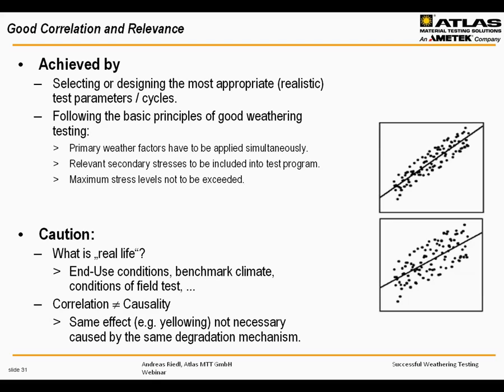So if you would like to test at, let's say, 5 sun level, then you have to check what we call reciprocity, which is, very simply spoken, the effect that two photons of a certain energy cause exactly twice the damage of one photon of that energy. This is reciprocity, simplified, and you should check that. If you are not sure, then don't exceed one sun level. Also with the temperature, don't choose a temperature which is higher than the maximum temperature occurring outdoors, or occurring in end use, I should say.